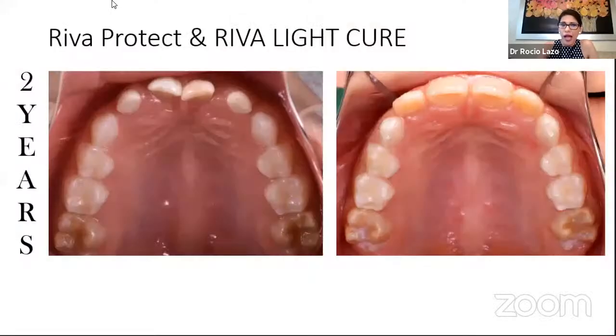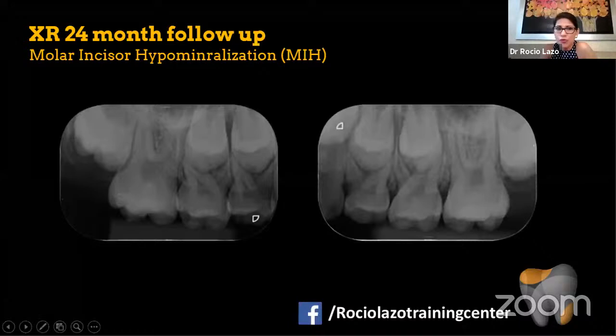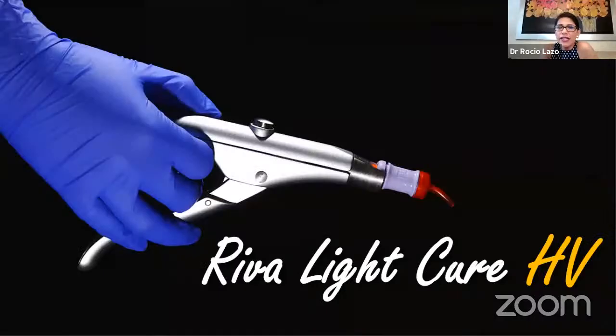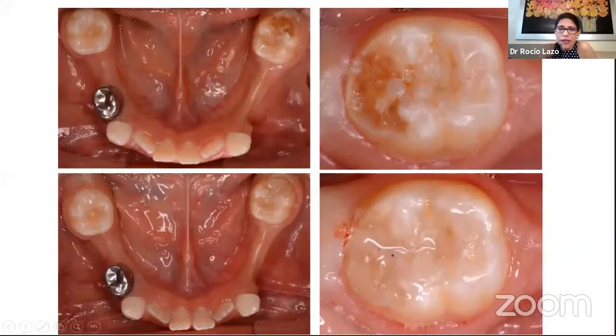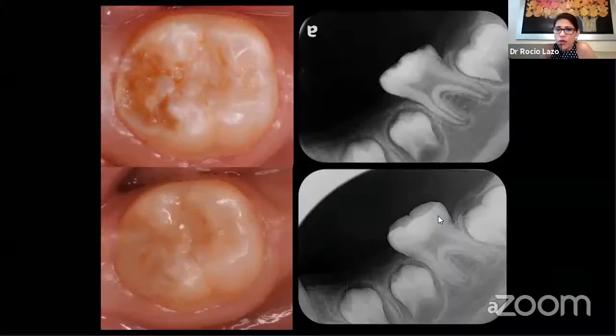Look here, the follow-up, 2 years, using the Riva Protect, which is a glass ionomer sealant that has strontium and perfect adhesion. You didn't have any problem. The follow-up at 24 months, perfect. And in this case, when the cavity is big, more open, I prefer to use the Riva Light Cure High Viscosity. Look here, great results. Look here, it's perfect. The sealing is perfect. Why? Because the strontium simulates, or substitutes for, the calcium that this hypomineralized enamel tissue needs.